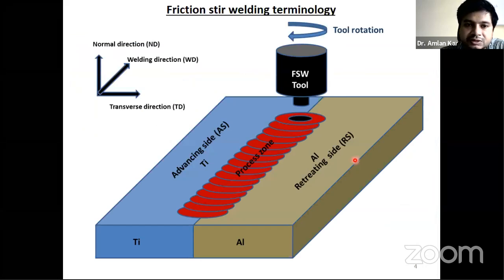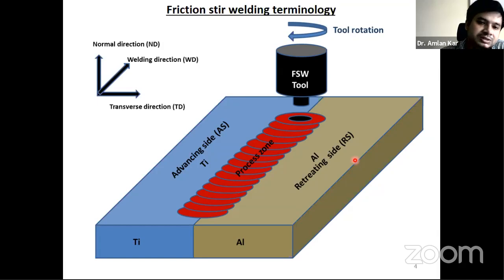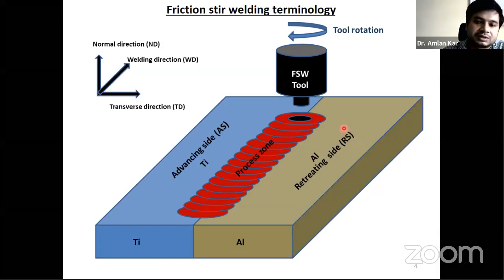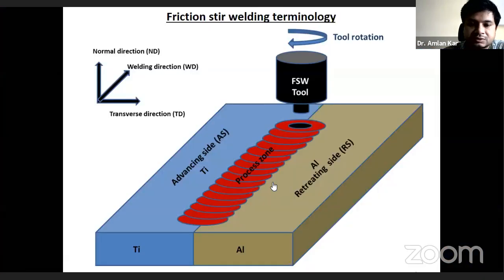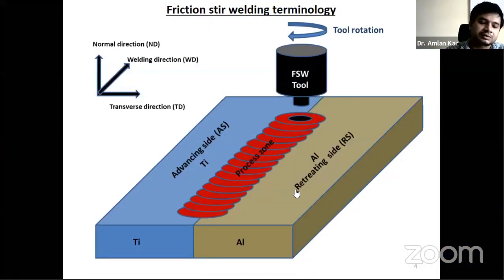So now I'm moving to friction stir welding. Just see what friction stir welding means, then you can easily visualize. If you want to see friction stir welding, this is a schematic view. You can see the tool being rotated, and it consists of a shoulder and the probe. When the probe is inserted into the abutting interface, the probe is inserted into the material, but not the shoulder. The shoulder has only touched the surface.